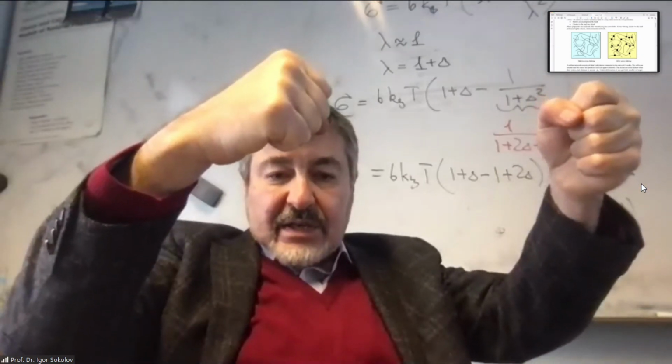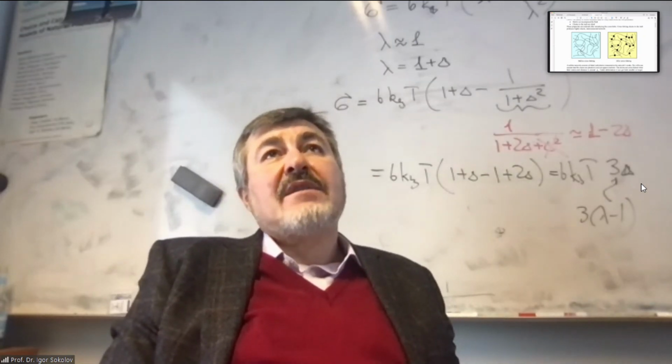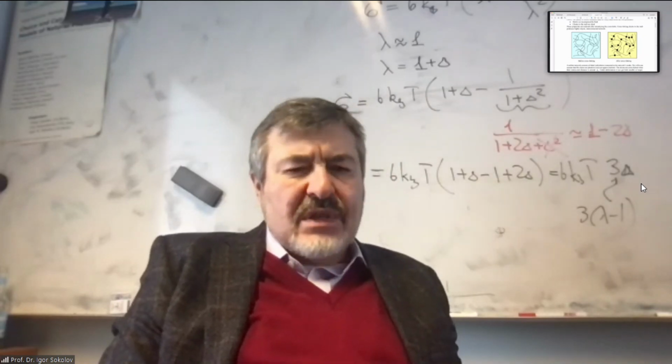So this is the other thing. All these solid properties, the elasticity returning back to the unperturbed state if you stop pulling on it, start above some given concentration of cross-linkers. At this concentration of cross-linkers, something very interesting happens. And very similar phenomena describe also other physical effects in polymer physics and far outside polymer physics, including semiconductors and so on. And this is what I would like to talk a little bit about tomorrow.